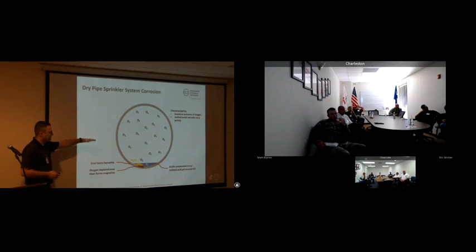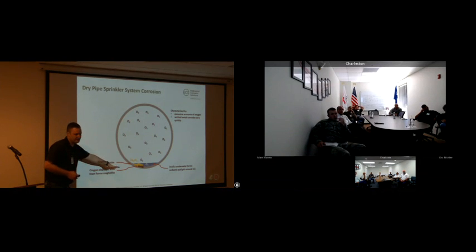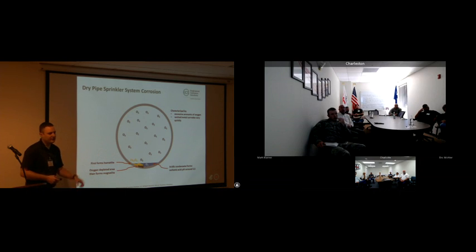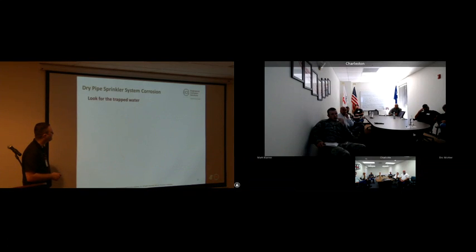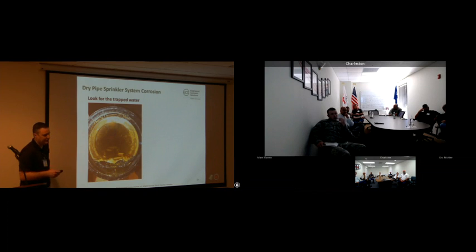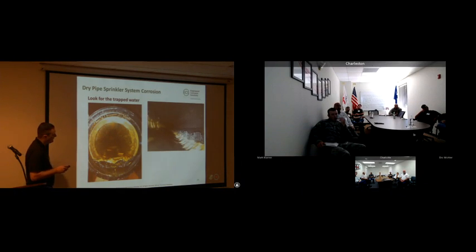So this is the same illustration, but as you can see, we just have a much thinner pool of water. As we discussed, the thinner the pool of water, the quicker the oxygen can dissolve and react with the pipe, and the faster, more aggressive your oxygen corrosion is going to be. So these are all pictures of dry systems, so you can see how much water is in dry systems. This pipe at one time was almost all the way full of water. You can see an air-water interface at the very top of it. You know, this pipe had significant amounts of water in it.